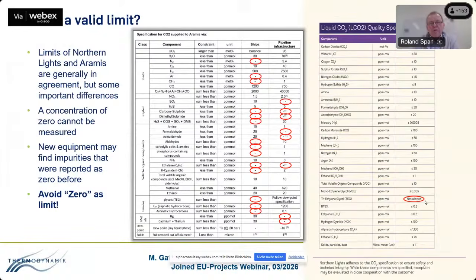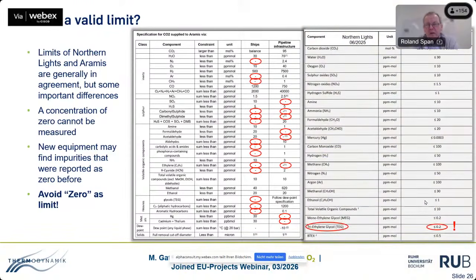So what we are looking for in CorEU mostly are means how we can specify limits for a multitude of components where we hardly have any information on phase equilibria or any experimental data on how they behave in these supercritical CO2 regions. And this is something that's in the latest Northern Lights specification now. The colleagues at Northern Lights obviously became aware of this problem. And if you look into the new specification, we have something like a 0.2 ppm limit for TEG. So we do have a non-zero value. And that's important. Frankly speaking, I cannot tell how profound these 0.2 ppm are and where they come from. But it's not zero. And any reasonable limit is better than zero if we define specifications like that.